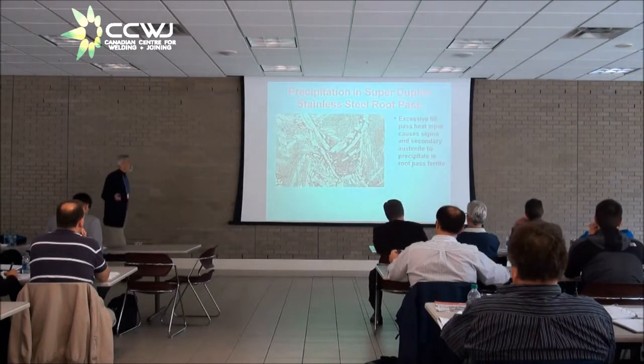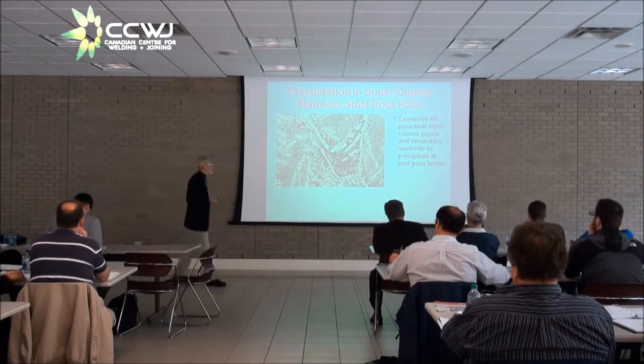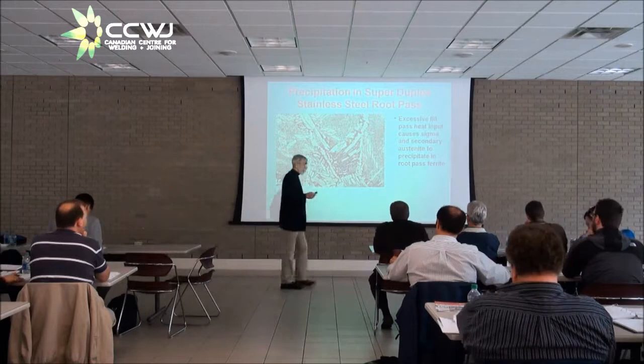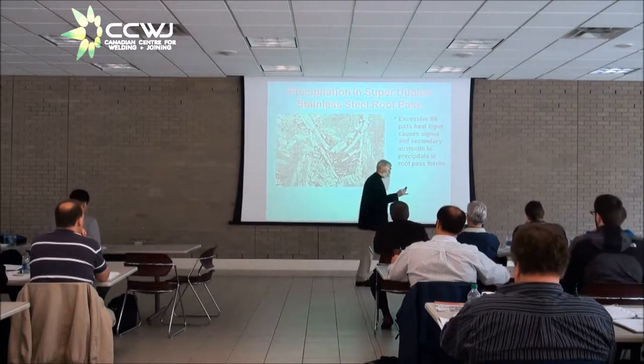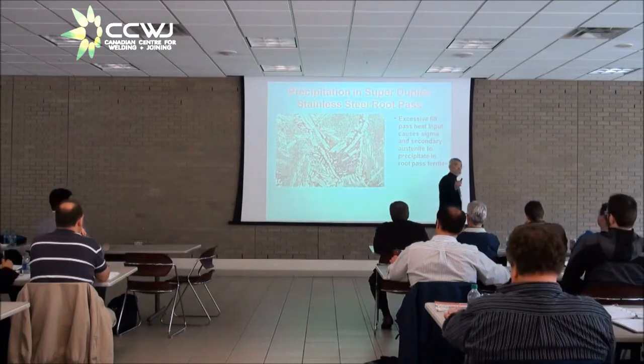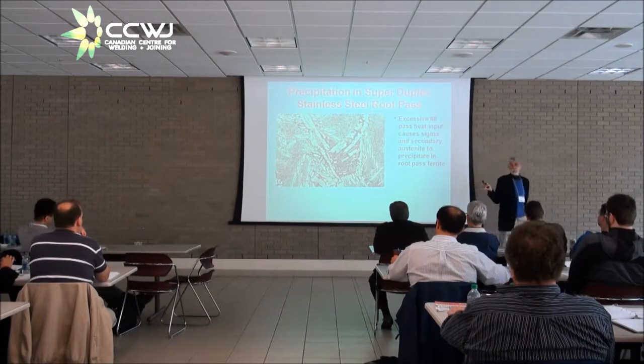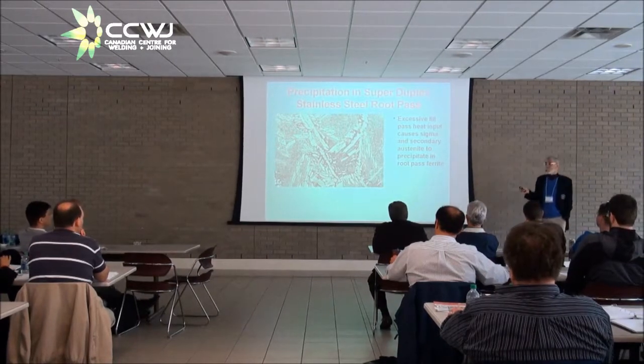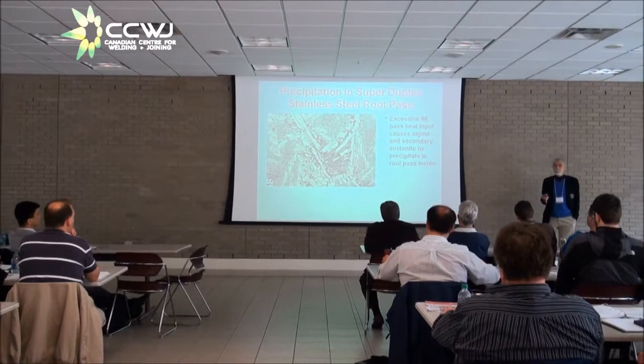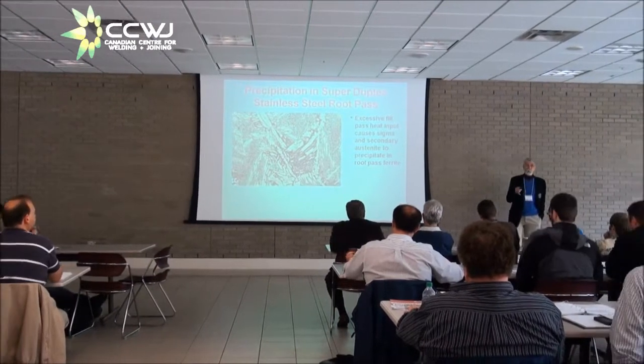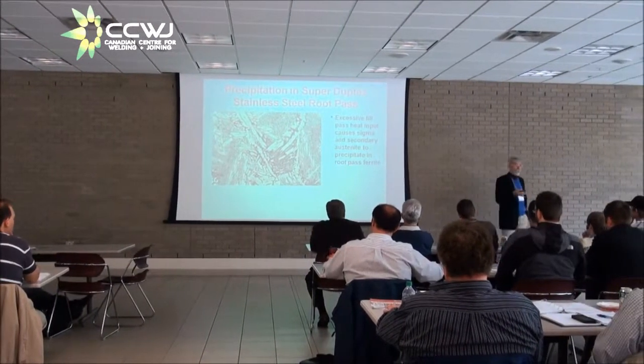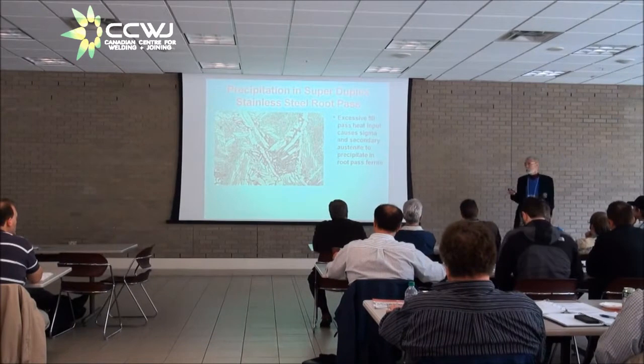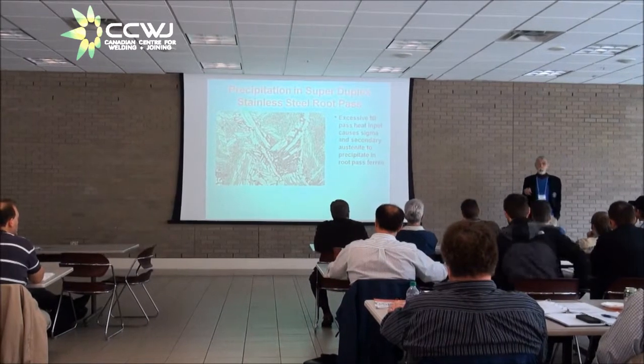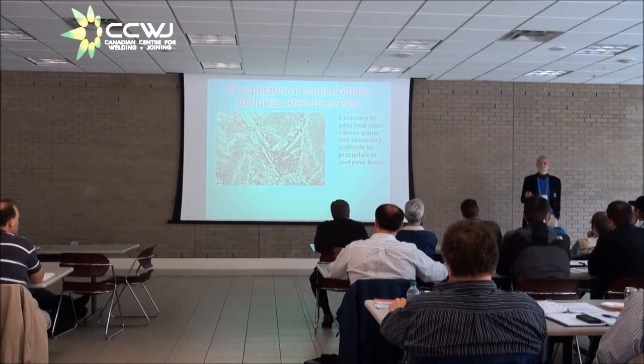Now, another thing that was referred to this morning, but I want to mention it again, perhaps to reinforce it. The worst pipe welder for duplex stainless steel is a guy who learned to weld pipe on carbon steel. And the reason is because when he learned to weld pipe on carbon steel, he learned a cold, fast root pass followed by a hot pass. And that's a bad thing to do with duplex, and especially with super.